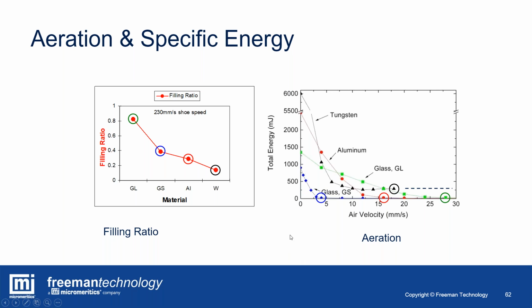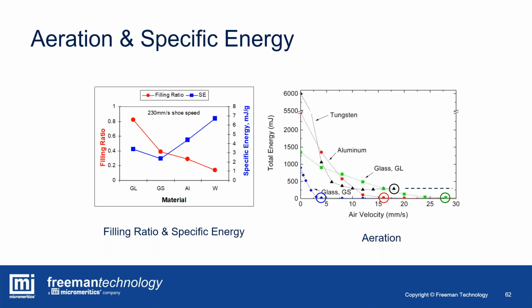So we can see 3 of these materials were non-cohesive materials. 1 was a particularly cohesive material in the case of the tungsten. And that's pretty robust. The tungsten is the worst performer, but there is significant difference in process performance between these 3 materials with the same levels of minimal or 0 cohesion. So let's have a look at the mechanical locking, the influence of shape. You can see that the spherical particles, the glass particles, are the lowest specific energy, whereas the angular and irregular shapes are the much higher specific energy. So that kind of makes sense.